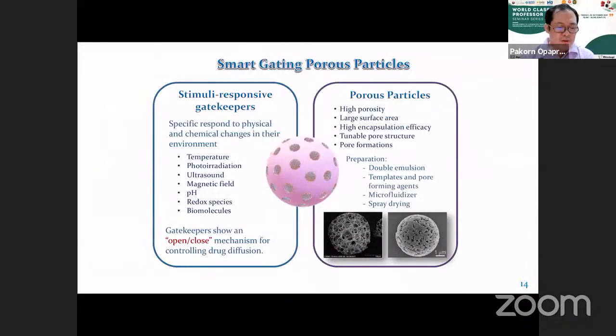In those review papers, one of the most interesting responsive materials that we pay attention to is the materials that can have smart gating behavior. In this type of materials, we prepare particles, nano or micro particles, which are porous particles, so they have many pores inside. As a result, we can load active compound inside the particles. To ensure a high encapsulation efficiency, we need to have a gating mechanism that can be closed or open when we change the environment of the materials.